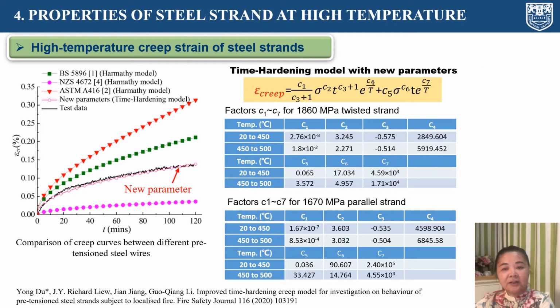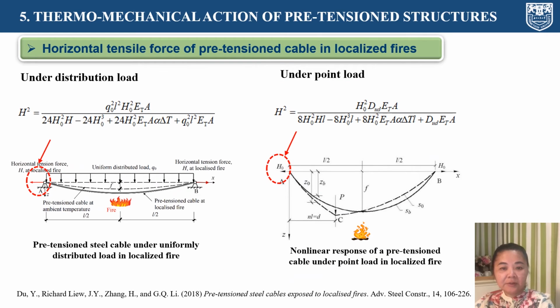A regression analysis is carried out to develop a set of new parameters, as listed in the table, for the time hardening creep model based on the test results of 1,860 MPa twisted strand and 1,670 MPa parallel strand respectively. Study on the temperature-dependent material properties and temperature distribution due to localized fires is given above.